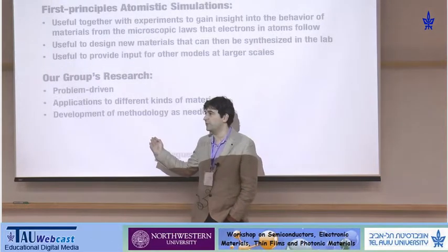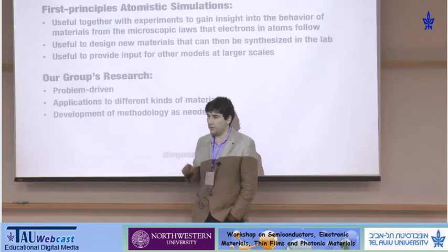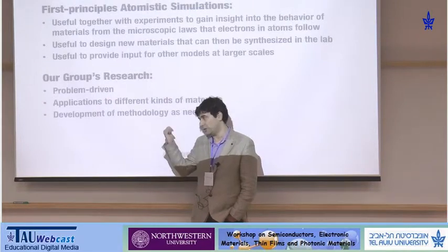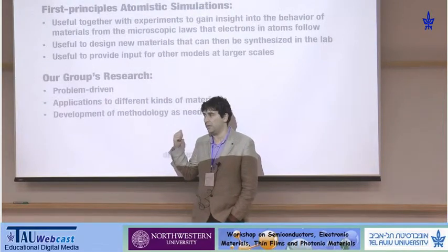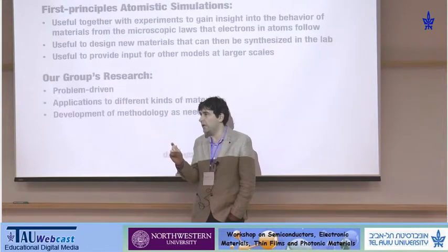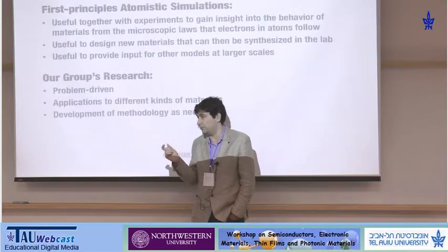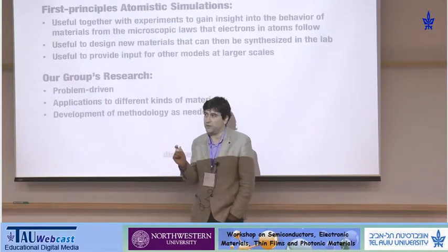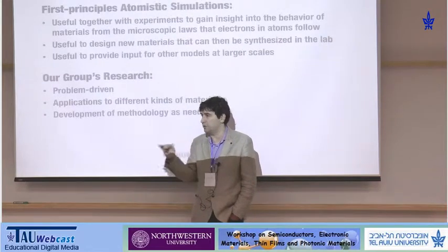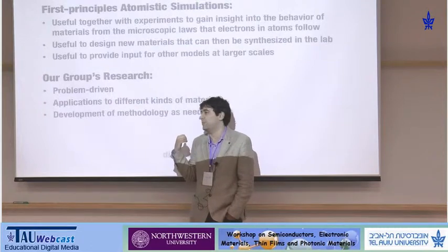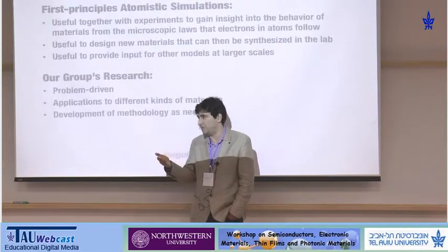Yes, in the case of bismuth ferrite, this is what happens. Experimentally, it was first found that there was this super tetragonal phase. Jorge and I and others found this phase, but it was not understood very well why the strain was so large and you still would get this, because in other things like lead titanate or barium titanate, if you compress it more than 2%, the material will create dislocations. This one is 6-7%, and it doesn't. But it's because there is the phase there already.